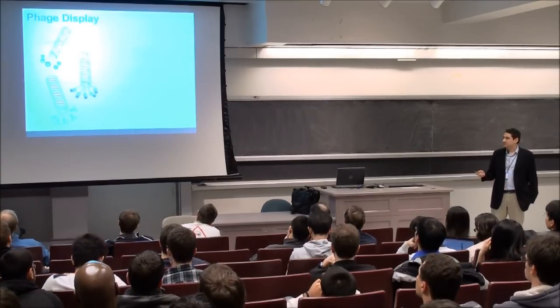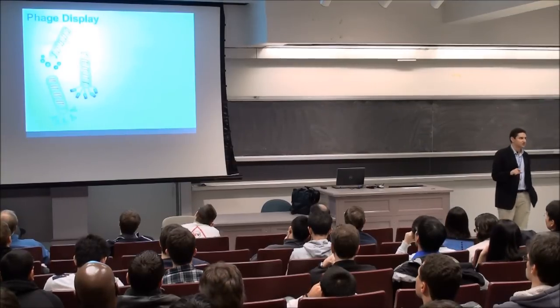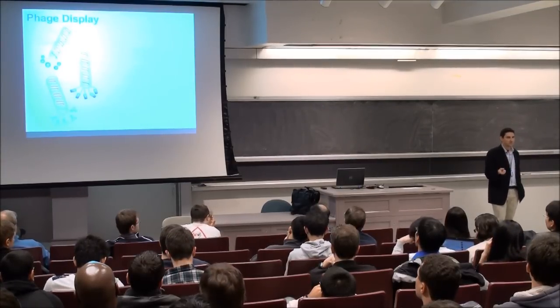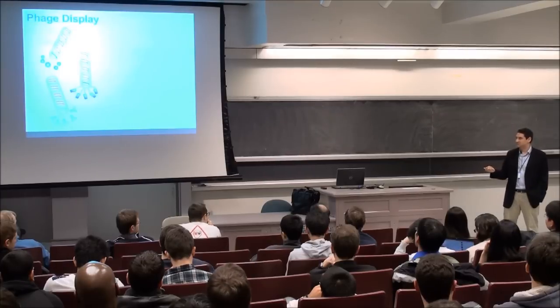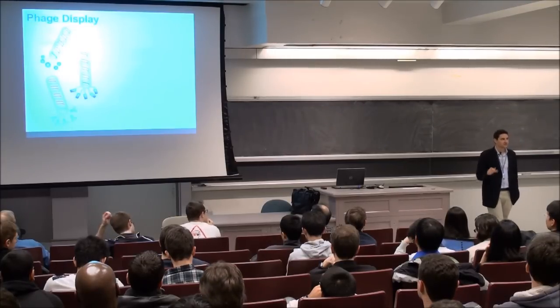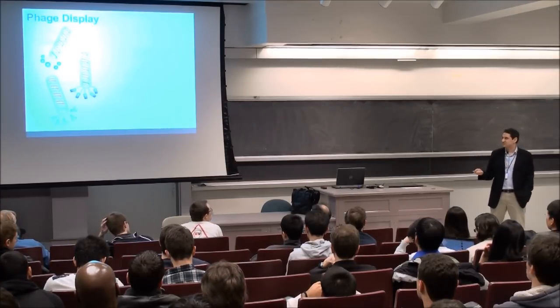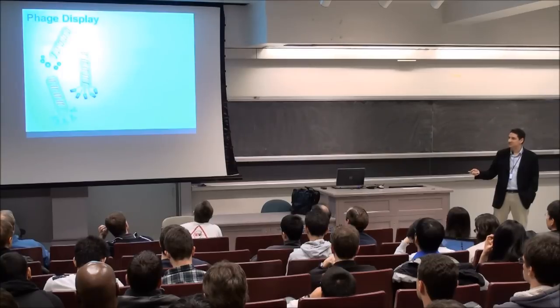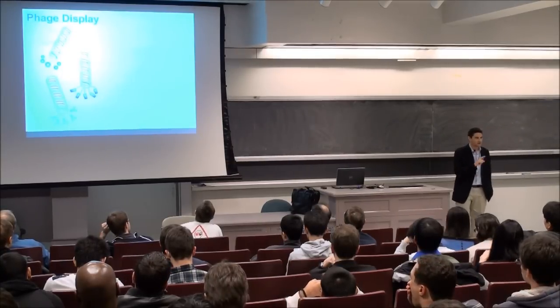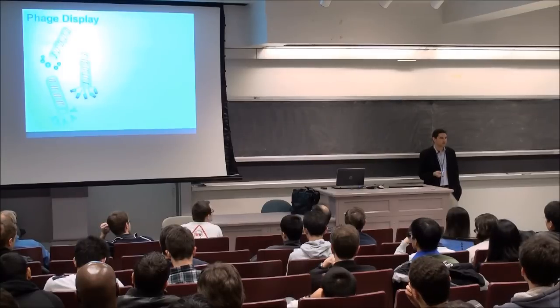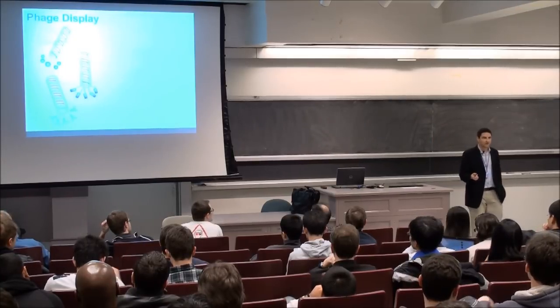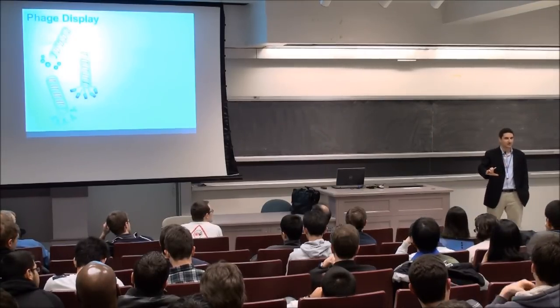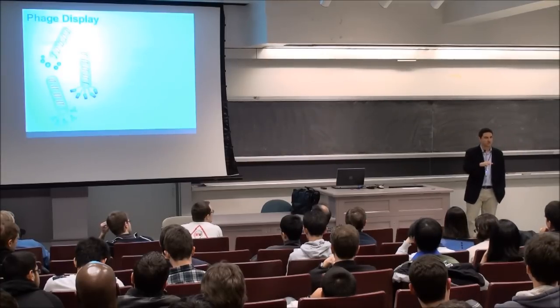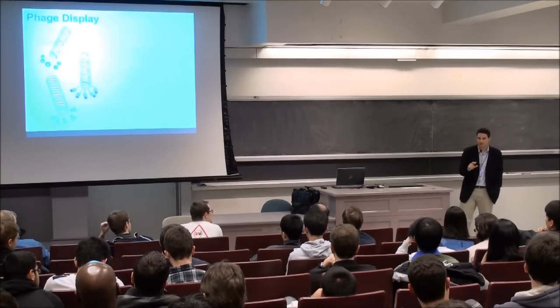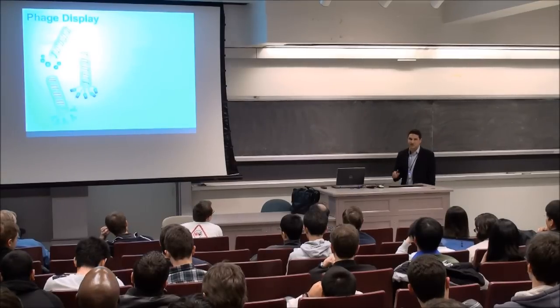And the approach we use to do this is an approach called phage display, where you basically buy this kit of literally 1 billion viruses. These viruses called phage, which infect bacteria. And each phage, at the terminal point of the phage, has this peptide on it. You can see by these different shapes, where each completely different peptide sequence on it, randomly generated sequence here. And you can then take these phage and throw it at your target, in our case graphene, see which one it binds and what don't bind. And then you can go back and figure out what those peptide sequences that bind, and say those are binders